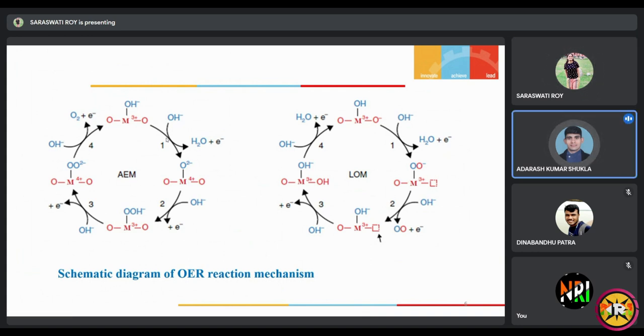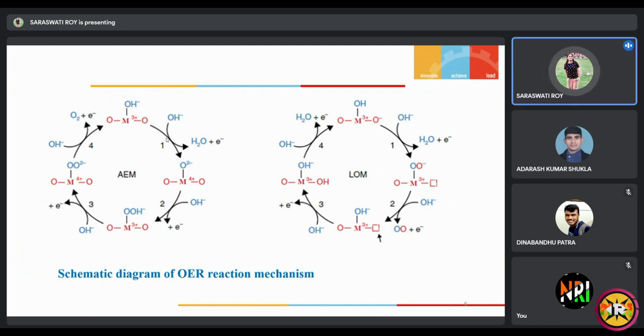So what I think is that if we wanted our catalyst to follow a single mechanism, we should change the conditions or change the substrate only. No, there is no need to change any conditions. Sometimes your catalyst will have higher oxygen vacancy, but it will not show the oxidation state change of your materials. So you don't have to change any conditions. Okay.